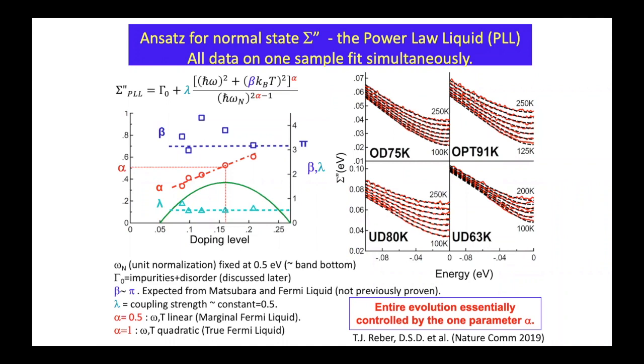So again, I put everything together. Let's just pick out, say, the optimal doped sample. This is our standard max Tc curve. The green is Tc. Here, I would pull an alpha term of 0.5. Something squared to 0.5 is linear. So it's linear in omega and linear in T, both. I'm measuring in omega and in T, both, and that's all simultaneous. And you can see for the many different samples, many different dopings, there are different families of this evolution.